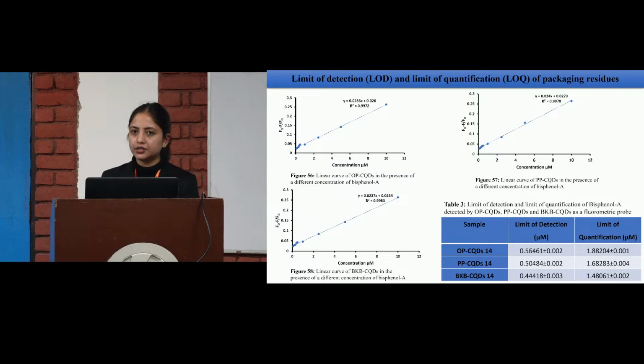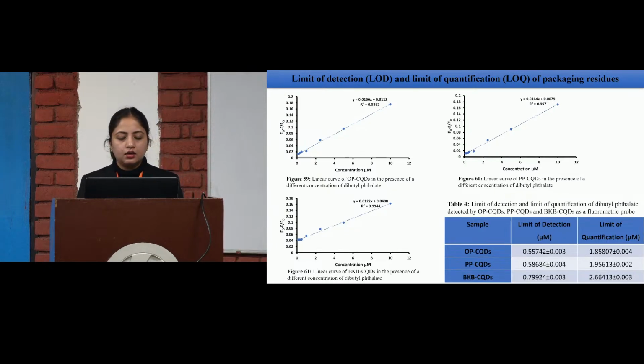Then the limit of detection, we get the limit of detection and limit of quantification by the linear graphs. We plot a linear graph with the higher correlation regression coefficient, that is 0.9, and we got the limit of detection of 0.56461 for the onion peel carbon quantum dot, for the papaya peel 0.50484, and for broken kidney bean the least limit of detection, meaning the least concentration. What is the least concentration we can detect with our sensors?